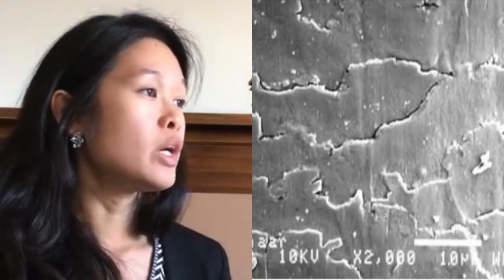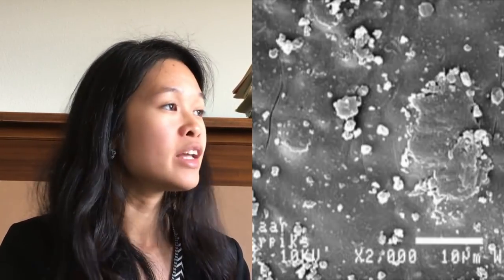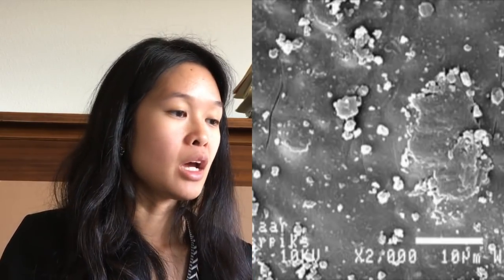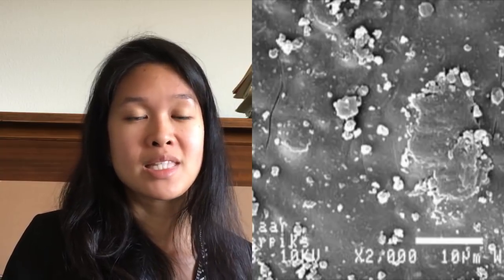What that tells us is that the texture of the hair contributes practically nothing — it's negligible — in terms of pulling and initiating string vibration. That makes sense if you've ever tried to play with a freshly haired bow with no rosin: you get essentially no sound. Now, comparing that image to one with rosin, you can see tiny particles of rosin dust clinging around the scales, with particle dimensions similar in height to the scales themselves. That's what allows the scales to grip and retain the rosin, whose stickiness increases friction between the bow hair and the string — and it is that friction which allows the string to be pulled, vibrated, and create sound.